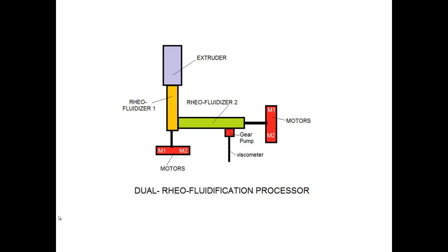So this is the equipment which I call the dual rheofluidification processor, which I've used to create the non-stability of a melt, which is sustained for a long time, and which we have been able to preserve in pellets, as I will show. I should also add that in the rotation of the cones, there are two cones, rheofluidizer 1 has one cone and rheofluidizer 2 has another cone. And in the particular examples which I will describe, the rotation in the two cones is reversed. In other words, it's counterclockwise in the first one and clockwise in the second.